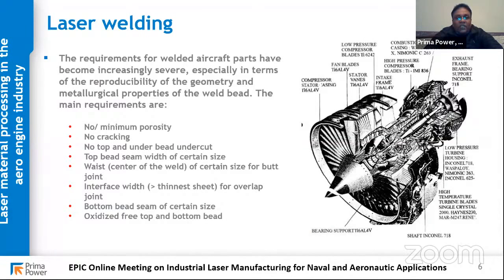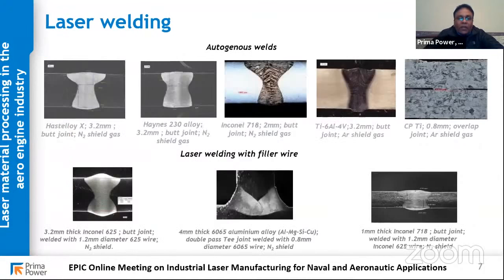The typical requirement in laser welding of aerospace material is not that cycle time is important, but the most important thing is the quality. So these are some of the things I highlighted: no porosity, no cracking. The weld width has to be a certain dimension, top and bottom, to give the strength. Most of these materials are either Inconel or titanium, so the gas shielding, or making the weld without any oxidation, is very important.